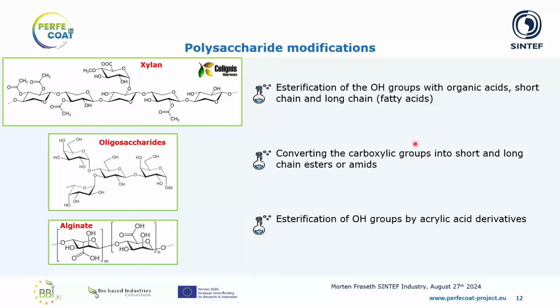The carboxylic groups can also be reacted into esters or amides by reacting with alcohols or amines, which can add hydrophobicity or other functionalities, for example, towards UV curing by introducing acrylic acids of different variations. It is also important that we can do the chemistry directly on the carbohydrate cycle here, but we quite often need a linker between the biopolymer or bio product and the actual functionality that we want to use as a cross-binder.